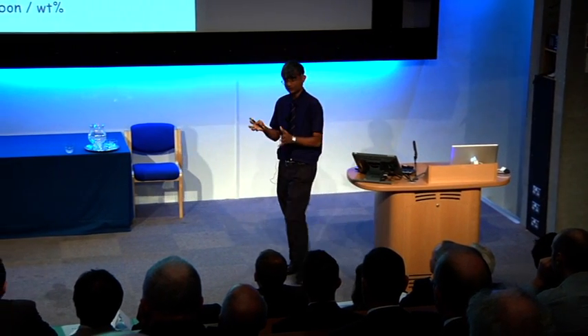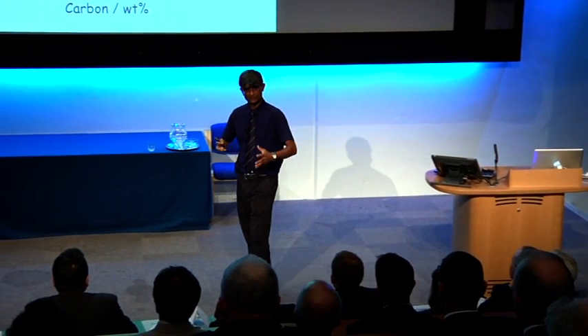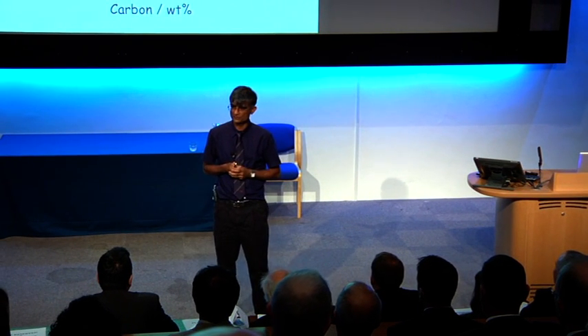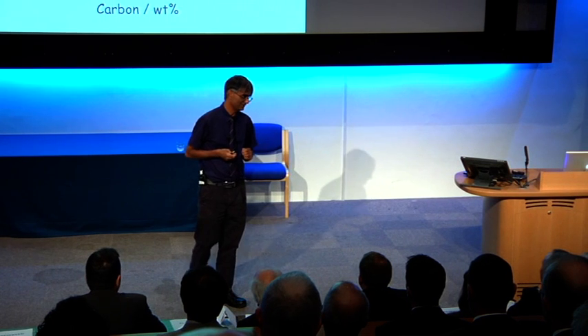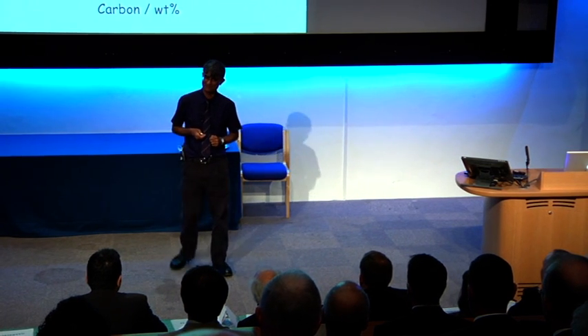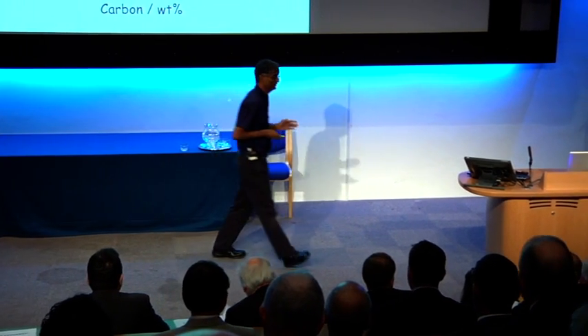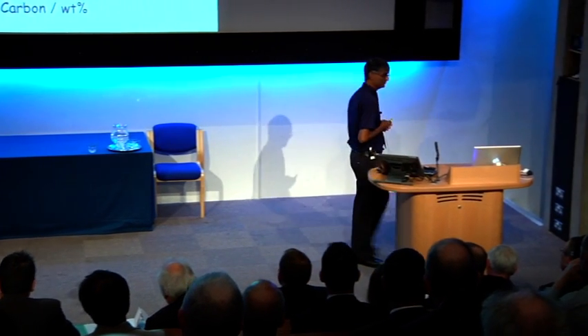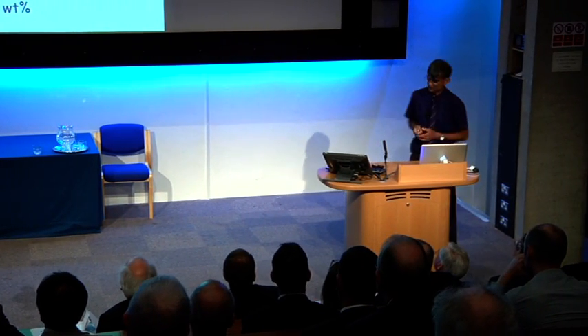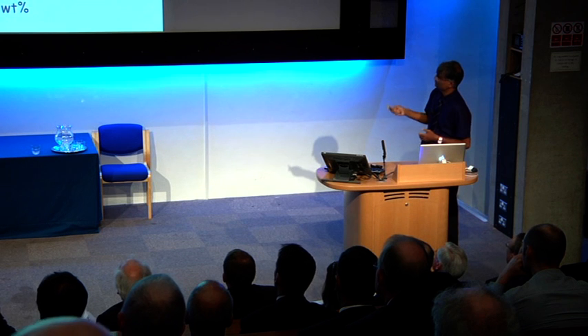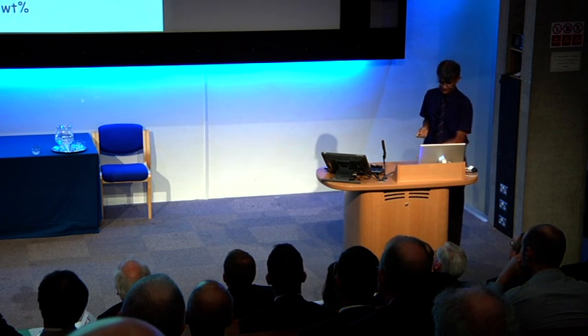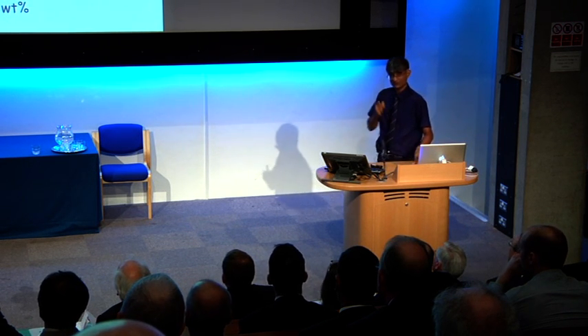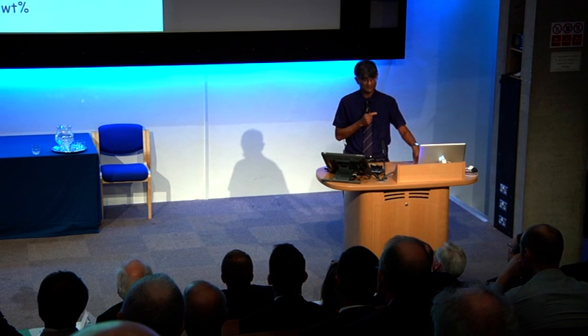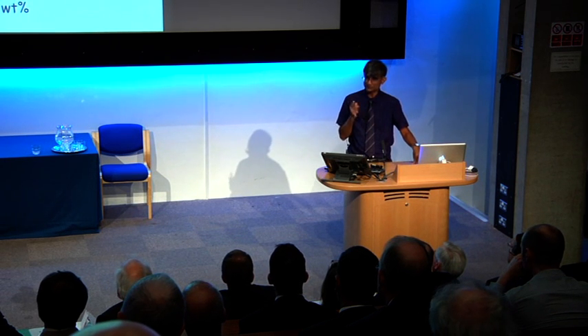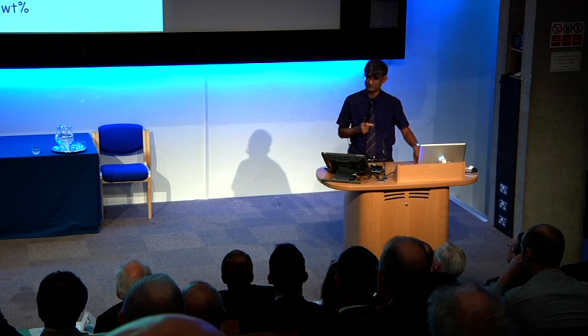So you would be treating this like good wine. You make the steel, you leave it for 100 years, and then you will get an incredibly fine structure. But Tom said that he is impatient. So we have to do this in a reasonable amount of time. And if we go towards 1 weight percent of carbon, then we have a reasonable amount of time of 10 days, at a pizza oven temperature. Now you might not think that 10 days is reasonable, but let me come back to that.